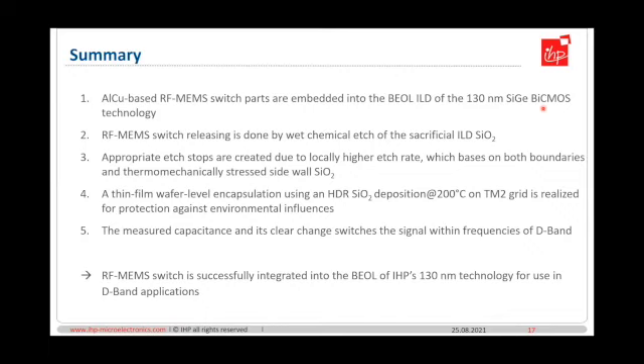Okay. I thought maybe the worst would be the sidewall metal, because you're using the via process to do that, right? The sidewall etch stop. Okay. Yes, you're using the via process. Would they allow big, long, wide vias like that? Yes, but we are talking about design rules, I guess. As far as I know, there are no problems. Of course, we also had problems with the TM2 grid. Therefore, we had to make exceptions. Also 1.5 micron holes related to 3 micron thick metal was not that easy, but some trials have shown that it's working and there's no risk for any other application or fabrication.